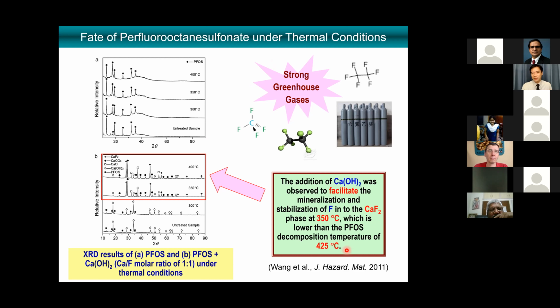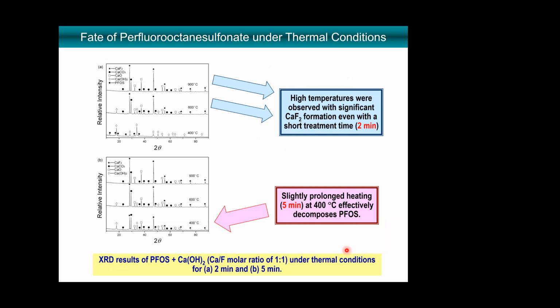What does that mean? That means we will not risk much chance for perfluorocarbon to be generated. Before the generation of perfluorocarbon, we already have the calcium hydroxide to react with the fluorine that stays in the PFCs. Then we stabilize the fluorine instead of letting it go to air and become the perfluorocarbons. More interesting, this reaction happens really fast. If you are talking about, say, 400 degrees Celsius, again, that was even below 425 degrees Celsius, you only need probably at most 5 minutes. Then you can have that reaction triggered.